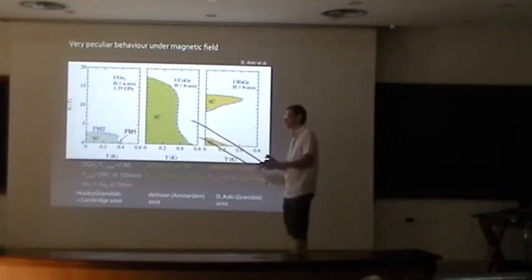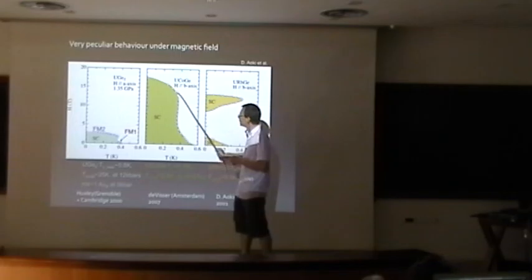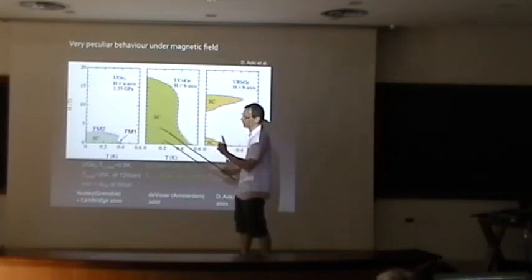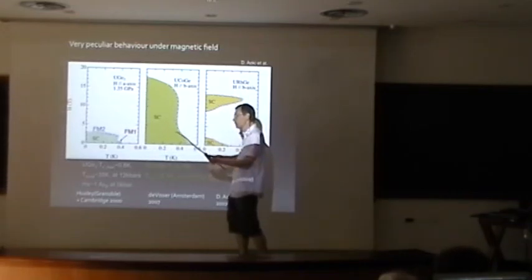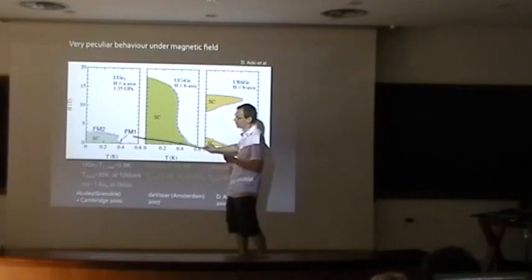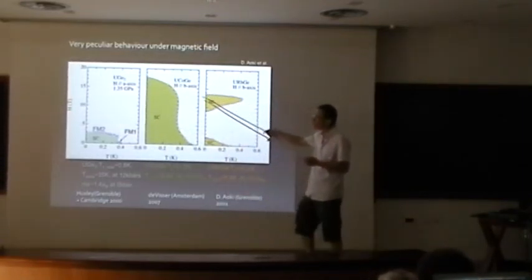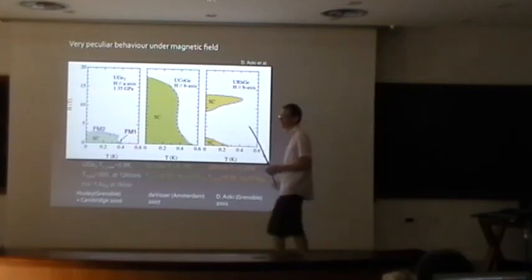It's not completely obvious, because if you have really two thermal effects which are strongly polarized, it's different. The problem is that the external field plays a small role compared to the internal field. So it's not completely obvious that this is a proof, because the difficulty is that along the C-axis, where you have this magnetization, you are within the Pauli limitation. You don't see Pauli limitation since you don't see any curvature of the HC2 curve, but you are below this Pauli limit. So this is the place where you would have liked to see that HC2 is higher. For directions which are not along the main axis of magnetization, you are well above, but you may find an alternative explanation. It's most likely that it is P-wave, but it is not directly proven. It is always very difficult.